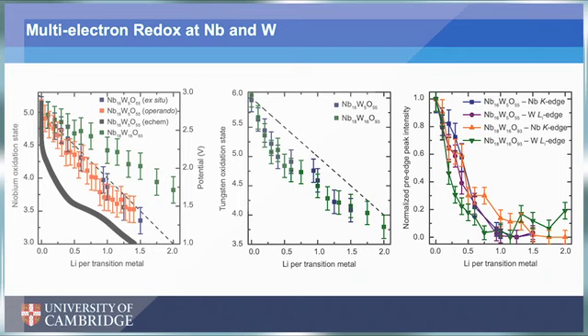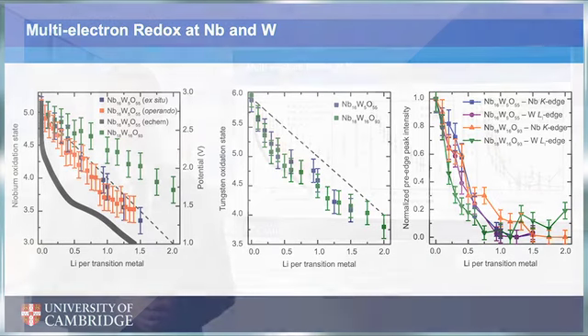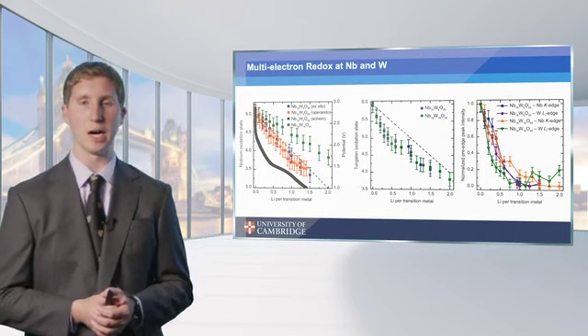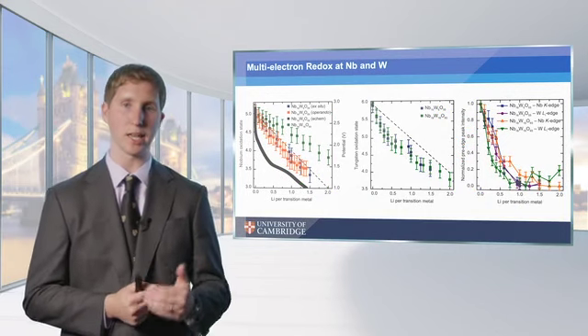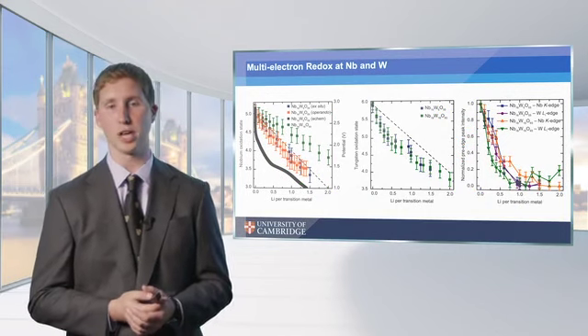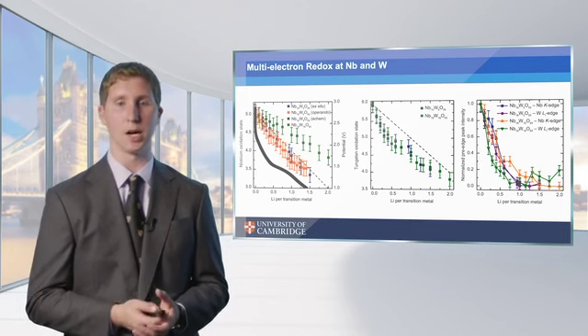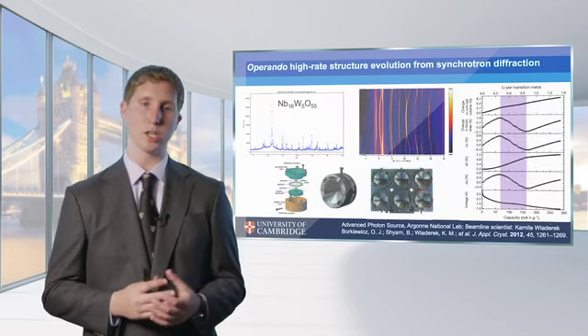And the pre-edge peak intensity, which is again an independent measure from the shift in the absorption edge, tells the same story. It says that both the niobium and the tungsten are being reduced at all states of charge. Those octahedra are becoming more symmetric, and this is occurring roughly linearly between the two transition metals, with a slight preference for tungsten reduction initially, and we observe that also in the slight increase in our anode voltage as we incorporate more tungsten.